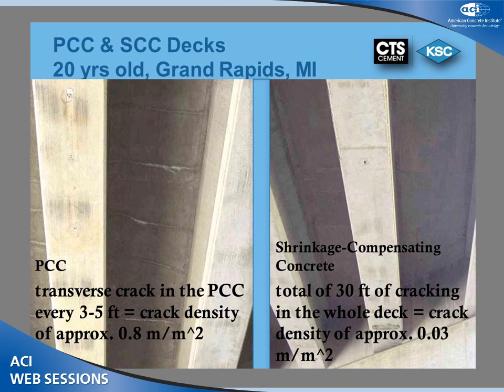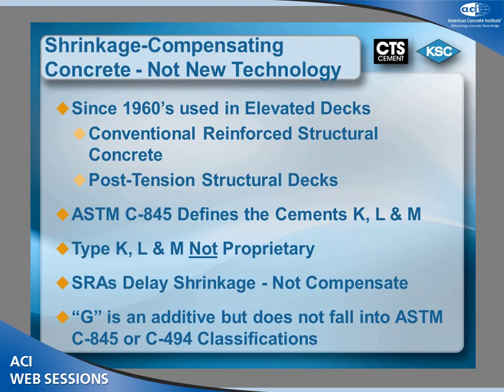If we start looking at these cracks as compared to the Portland cement concrete to the type K concrete, we're basically looking at the transverse crack density, or the crack density itself, being much greater than the cracks associated with the shrinkage compensating concrete. These two decks here were actually placed at the same time, 20 years old, and one was placed with the Portland cement concrete, and at the same time the shrinkage compensating concrete was placed. So we can see here what the results were, and this is carried forward with all the studies.